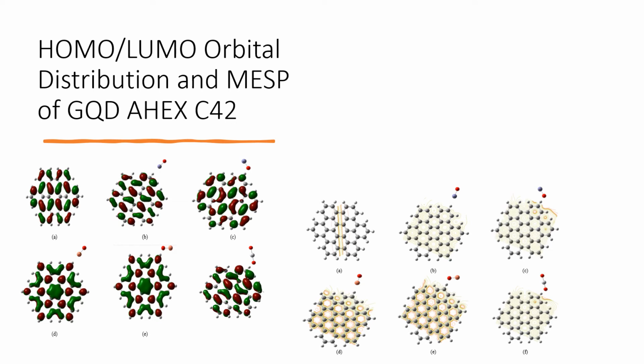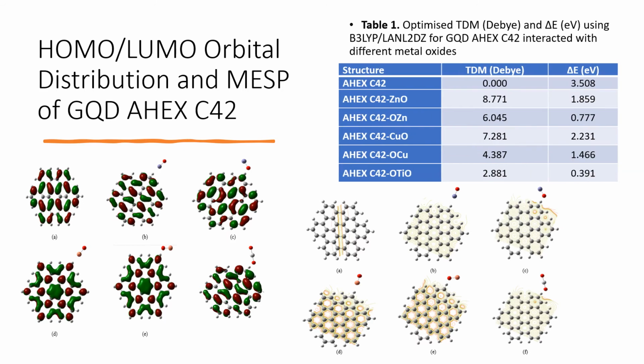For the graphene quantum dot armchair hexagonal form, metal oxide changed the orbital distribution and the color map of molecular electrostatic potential, which increased the reactivity of the graphene quantum dot surface. Also, total dipole moment increased while band gap decreased with the decorated graphene quantum dot with metal oxide. And the most enhancing metal oxide is titanium dioxide with band gap equal to 0.391.